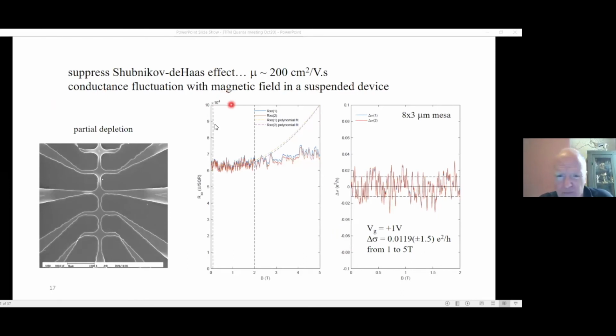What happens when we put a magnetic field on? So this is that same image again. I've used that image, I think, 3 times now. You can see breaks here. You can see freestanding. If we get the device into that variable hopping regime, we've got very, very high resistivity here, 60,000 ohms per square.